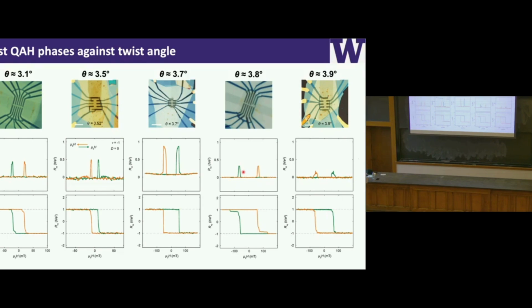That's because the topology is coming from these layer pseudo-spin skyrmions. Just to get on the same page, we're talking about filling factor. It's not a conventional filling factor for the magnetic field. That's correct. It's the filling factor of a band. Yes, exactly. Can you tell how you count nu? I mean, you have degenerate bands. So for example, nu equals -1 corresponds to what? To fully polarized. Yes, it's a filling factor 1. Basically, the top of the valence band is the filled moiré band. We're talking about the moiré band.